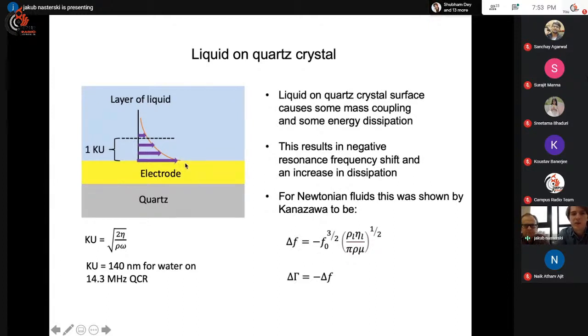with the quartz, because as you've seen on the surface, the water moves with the crystal. So the crystal sees it as additional mass moving. And there will also be additional dissipation, because the water layers shear against each other, so the energy is dissipated, it's lost. And the interesting thing is that the gamma, the increase in the dissipation, is the opposite of the decrease in frequency. So you can see how the dissipation is related to mass coupling.